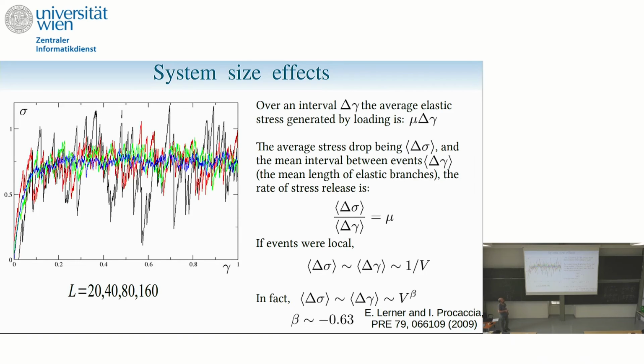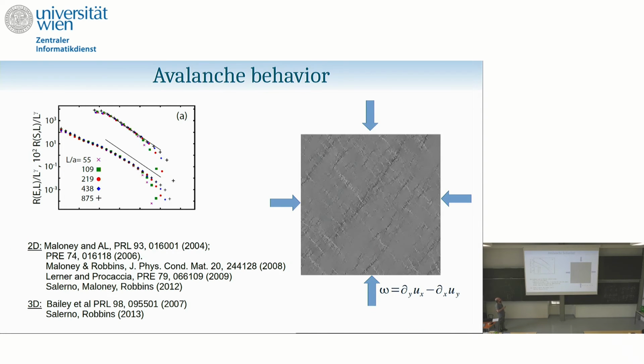And the fact is that, okay, I just cite one reference there, I'll cite many others later. In fact, there are some exponents, and there is a whole literature now on what the exponents are, and there were lots of efforts in that direction. Now the point is that the system converges towards a continuous curve, but it converges not as fast as if events were independent. You have much larger fluctuations than you would have if events were independent, right? And so that's a direct trace of this avalanche behavior. Here I just refer, I think this is from Salerno and Robbins, if I'm not wrong, in 3D, some scaling with system size, and there is a whole lot of literature. I like this picture, it's from Salerno, I think, or maybe Maloney and Robbins.